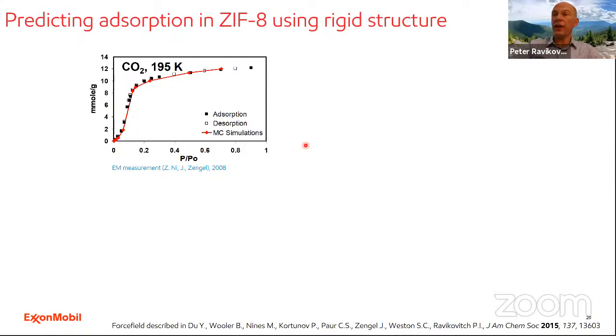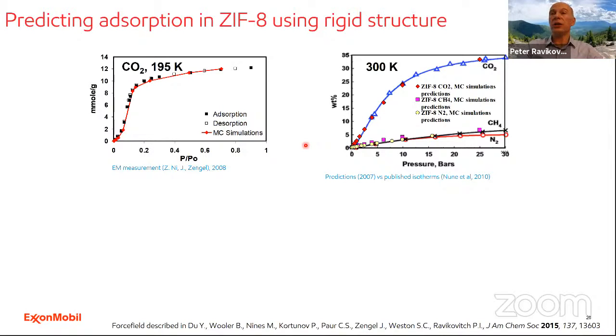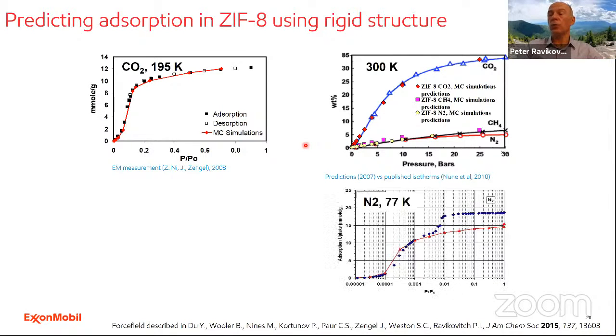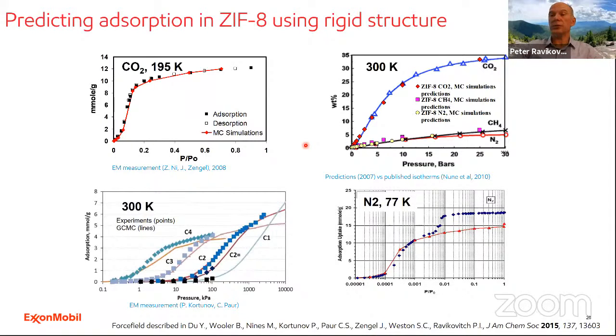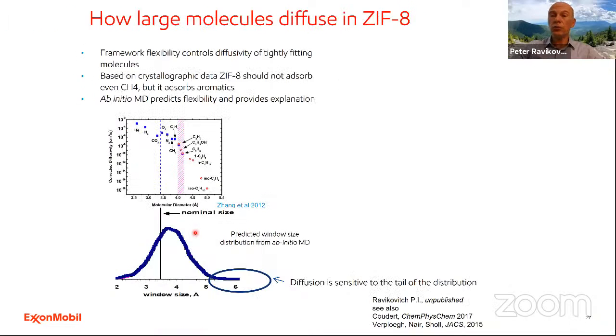For instance, for this ZIF-8, which has a rather large cage, if you use classical molecular simulations with the rigid structure and appropriate force field, you can actually predict adsorption of simple molecules pretty well, in very good agreement with experiments. These examples for CO2, methane, nitrogen, and even for some light hydrocarbons, have very decent agreement. For diffusion, however, it's more complicated.